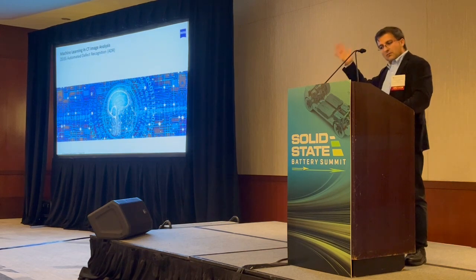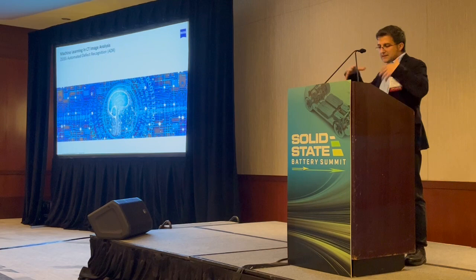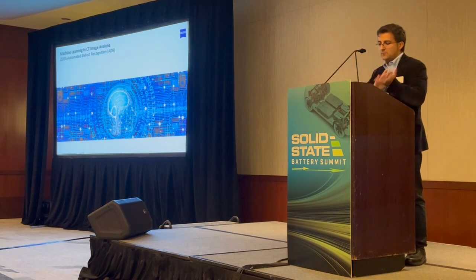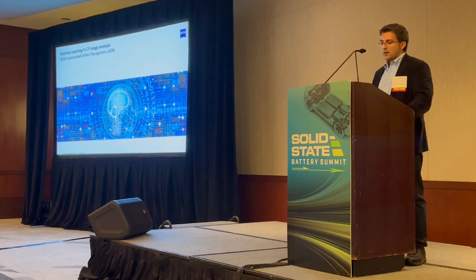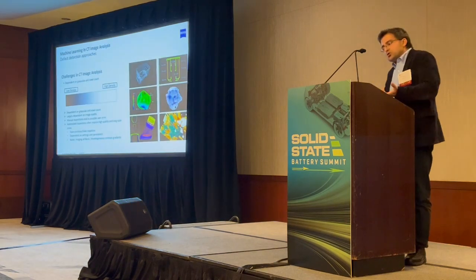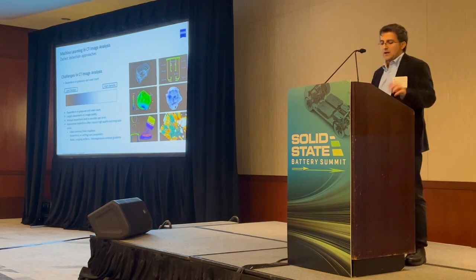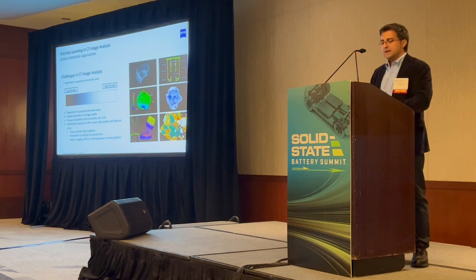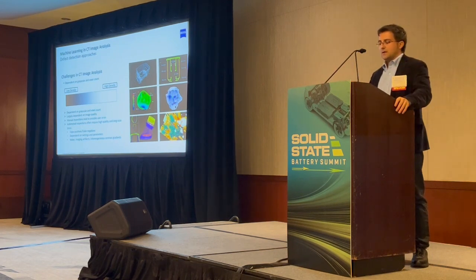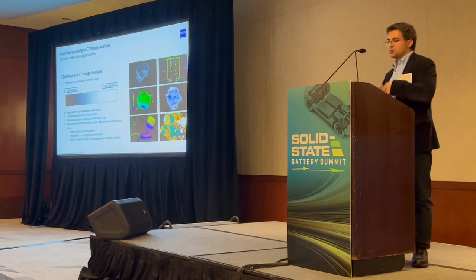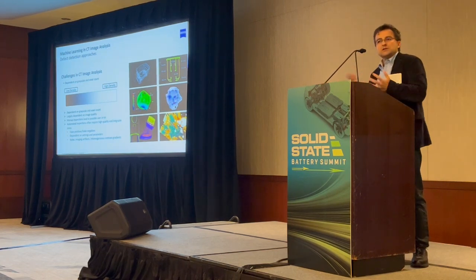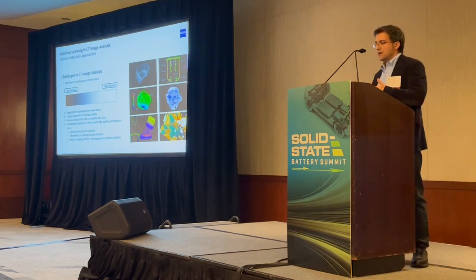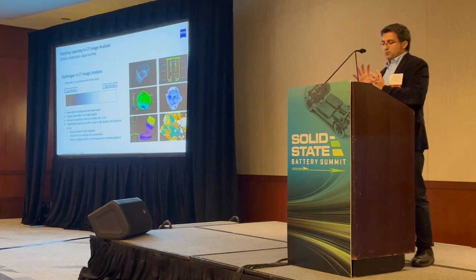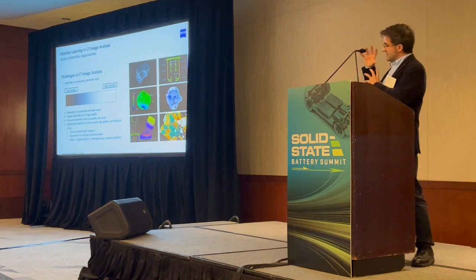In the post-processing, there are other companies that are using it, and it's by basically taking the data that you collect from 3D and now applying some deep learning algorithm to try to improve the data, or do some type of defect detection. What happens in X-ray CT is that you collect data and the data comes in a grayscale level. And you use the data to do several types of inspections, like check for porosity, inclusion, maybe weld defects, size and shape errors, and many others. But the volumetric data, the 3D data that defines each voxel, is in a grayscale value.